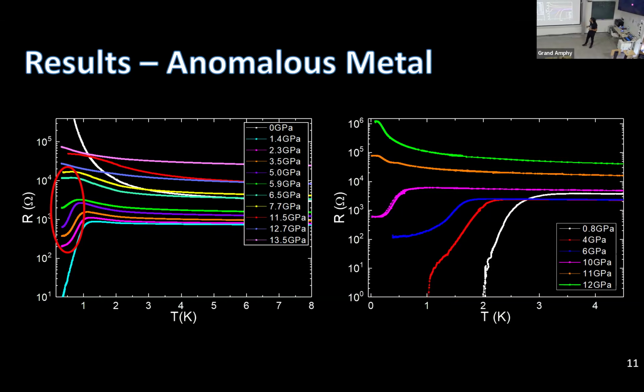which indicates we have some metallic phase, both the M1 and M2, inside our indium oxide, which was very, very surprising for us because we measured indium oxide in our lab for many, many years, and we never saw this anomalous metallic phase in our indium oxide samples. Changing the magnetic field, changing the thickness, changing the disorder, we never observed these anomalous metallic states with other tuning parameters. Pressure was the first time that gave indium oxide the opportunity to show this anomalous metallic phase, and the fact that we measured our anomalous metal in the same system where we never saw it before was the first indication that this is a real effect in our sample.